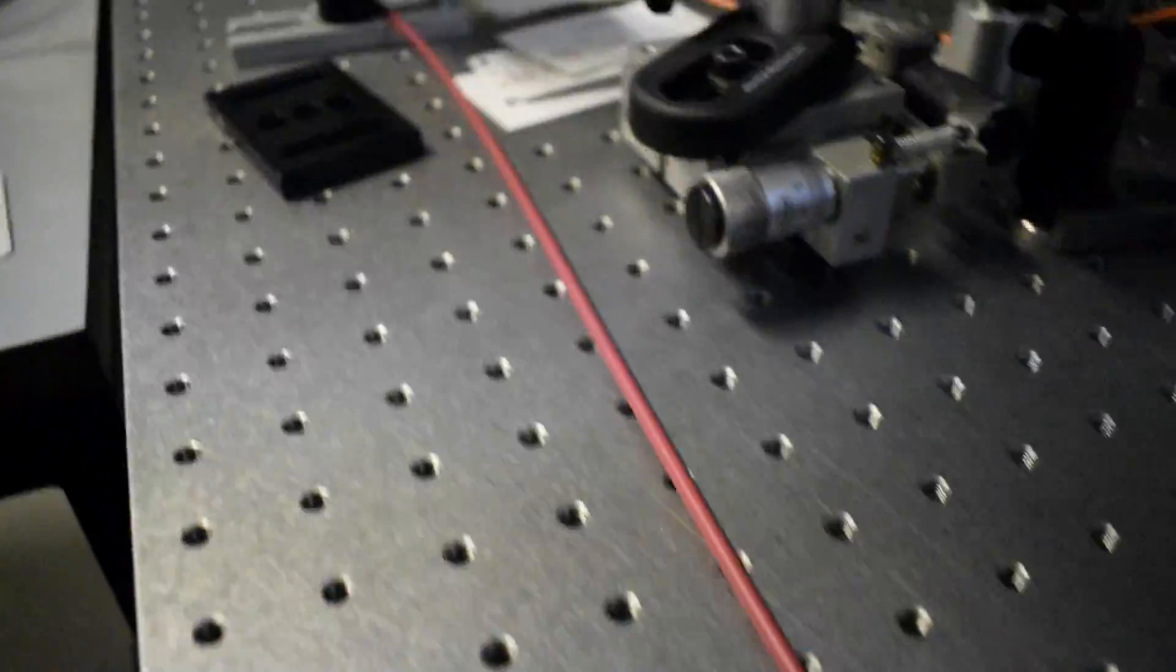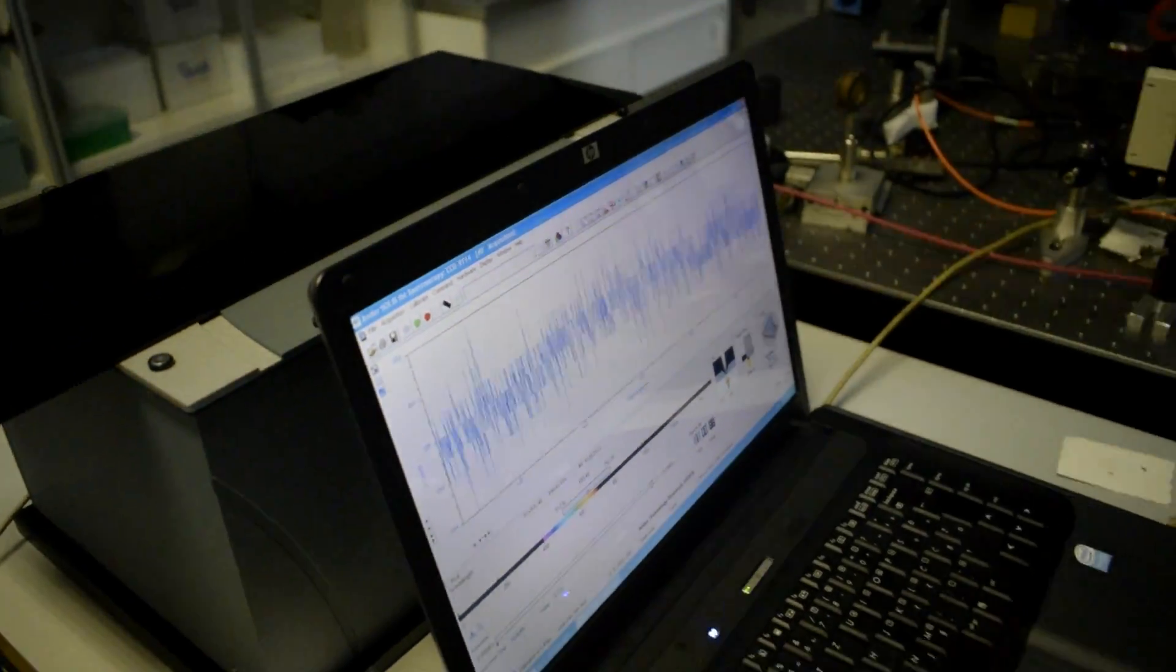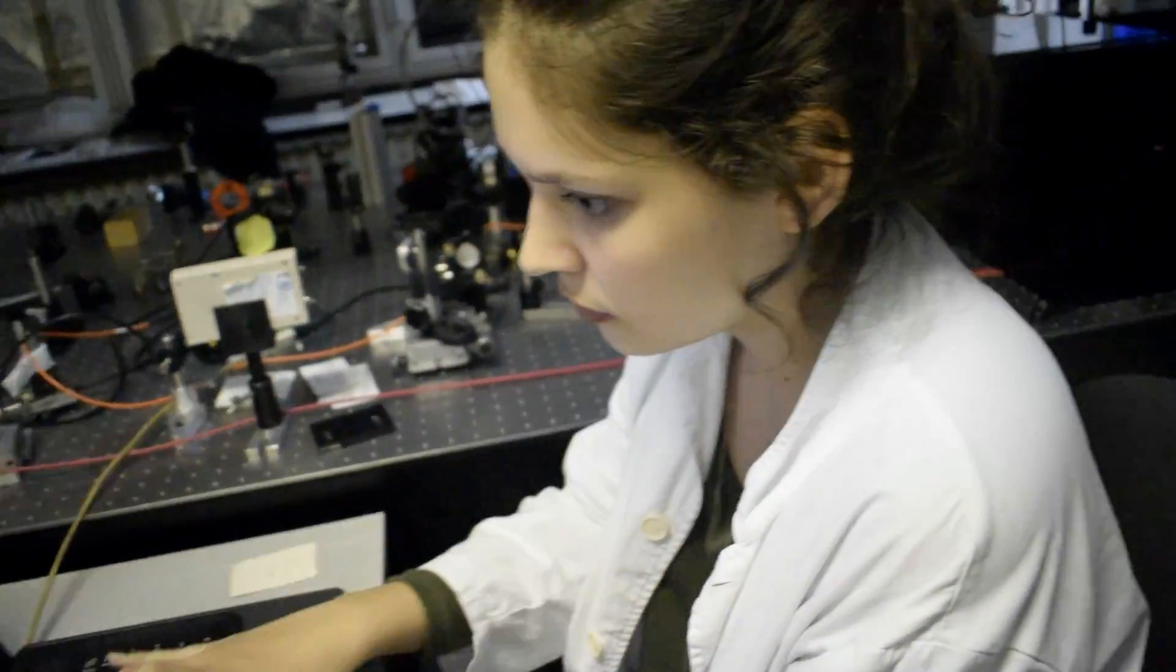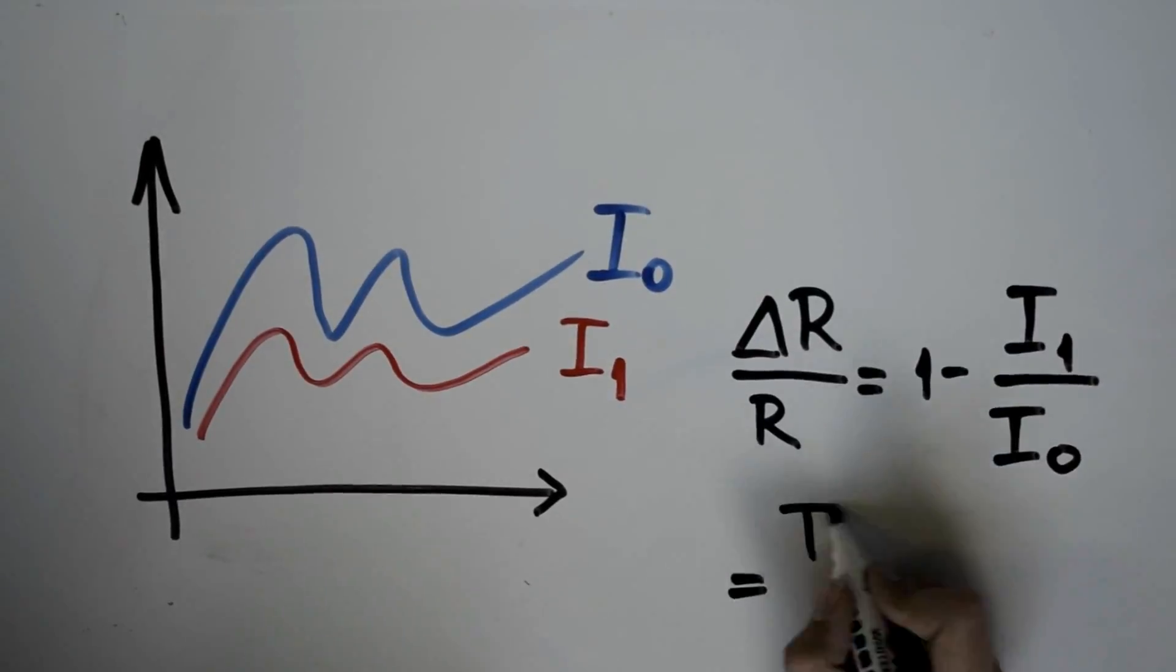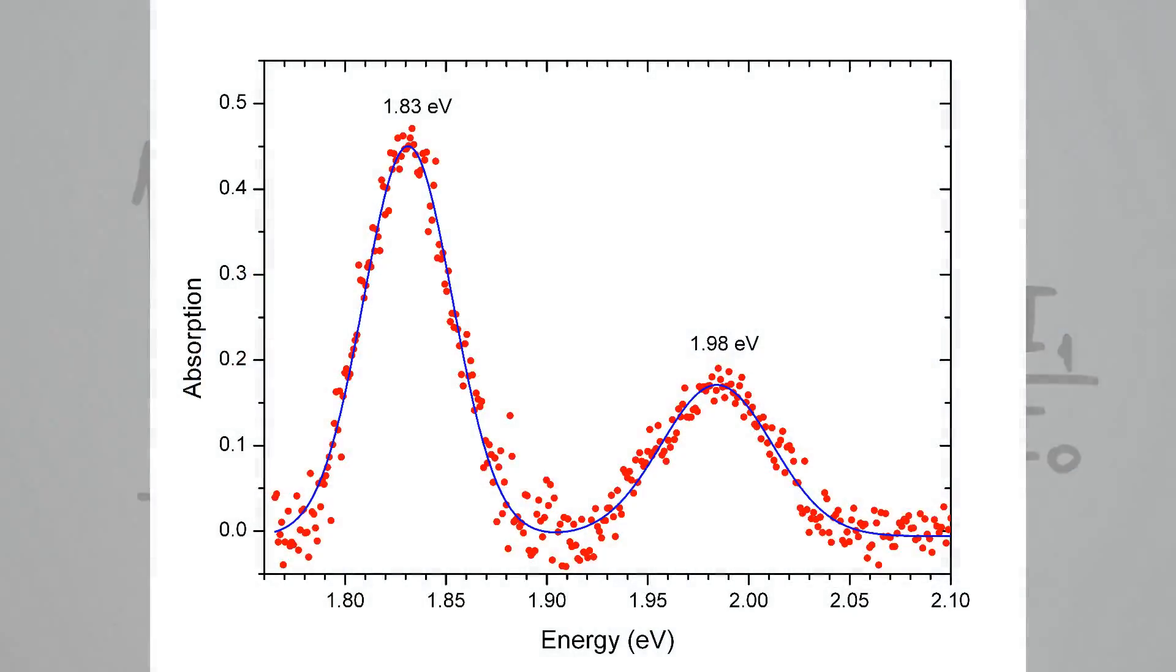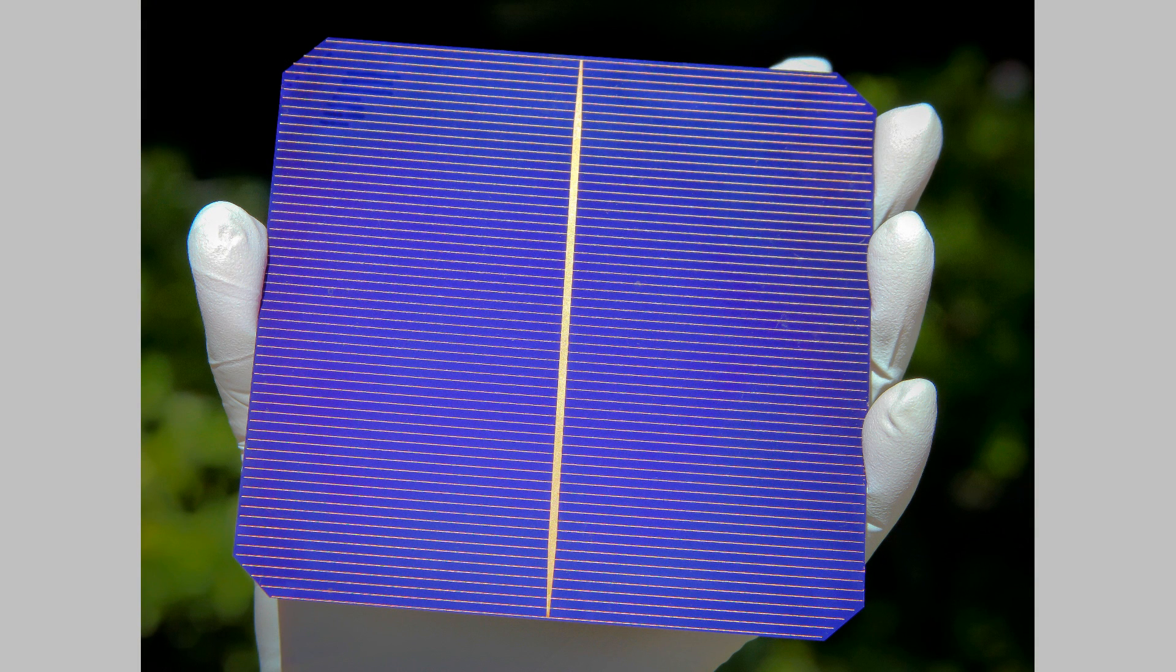With optical fiber, the reflected signal is sent to the spectrometer, where it spreads out and is assigned to a specific wavelength. The results are an absorption spectrum of our sample. What we noticed was that MoS2 has great light absorption, and since it is a semiconductor, that makes it a perfect material for solar cells.